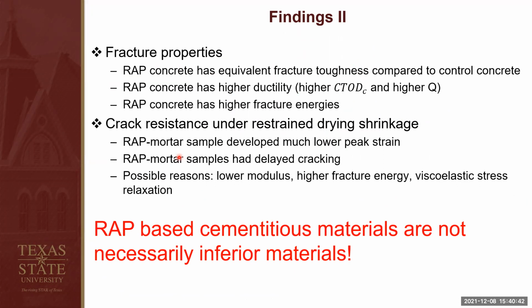Here I'm also drawing conclusions for the second part of this project. For the fracture properties, we found wrap concrete has equivalent fracture toughness compared to the control concrete, and the ductility of the concrete can be improved by adding wrap. And the wrap concrete also has higher fracture energies compared to the control concrete. For the cracking resistance under restrained drying shrinkage, wrap mortar samples developed much lower peak strain, and by adding wrap, the mortar samples also have delayed cracking time.